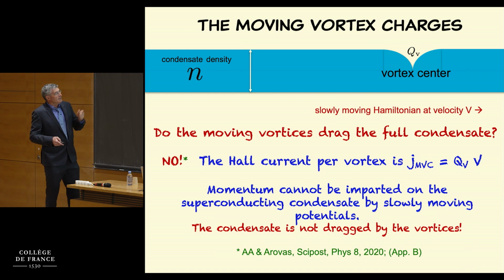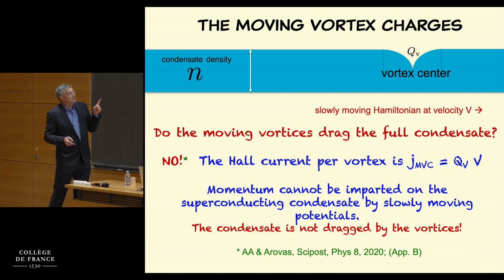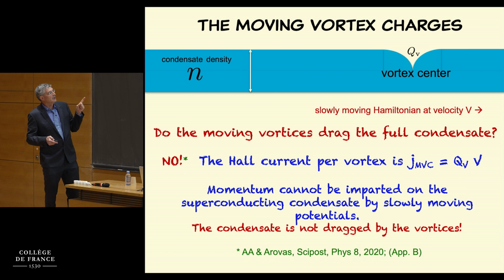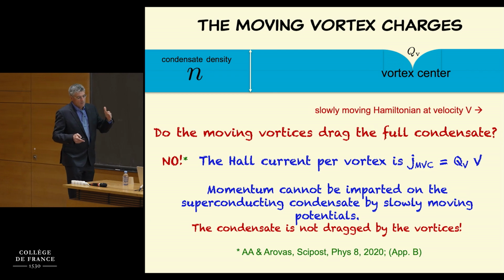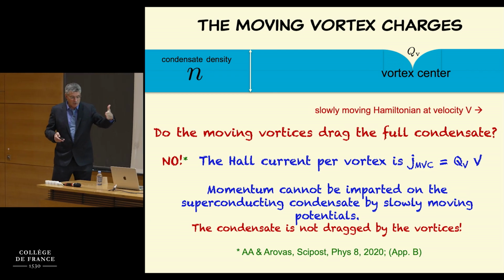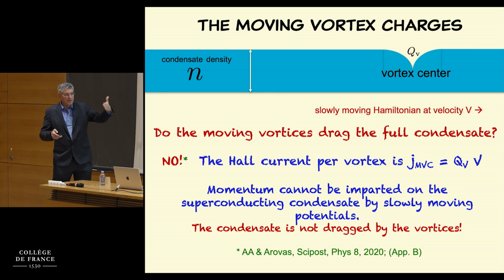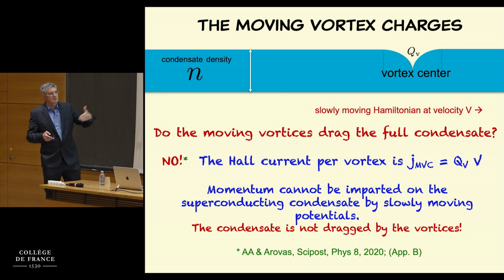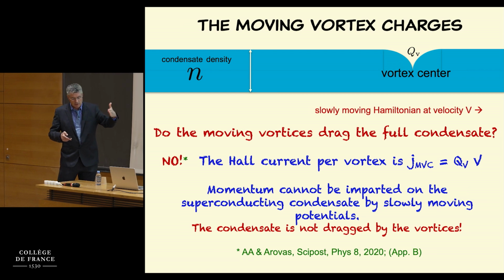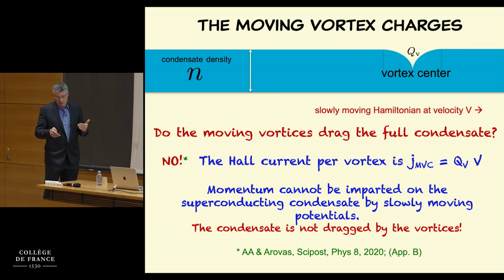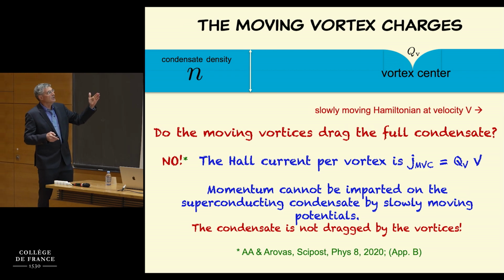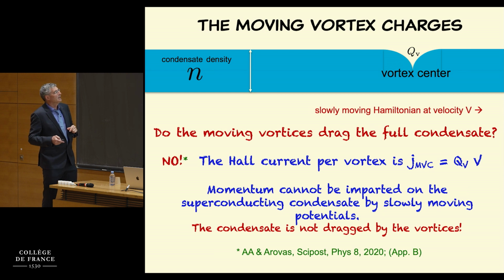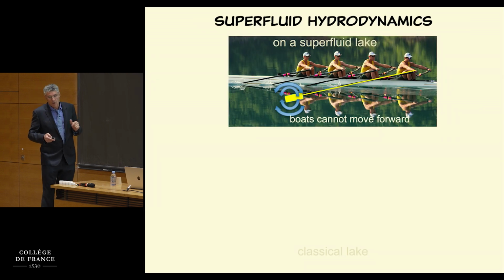Its momentum cannot be imparted on a superconducting condensate by slowly moving potentials, and you cannot drag it. In other words, if you move a potential, and a vortex position is like a potential, it's coming from the fact that the Hamiltonian has essentially a vector potential that tells you where the vortices are, and when you move that potential, you will not move the superconductor if you do it slowly enough, because the superfluid is rigid and attached to the frame it was prepared at. So this is known, okay?